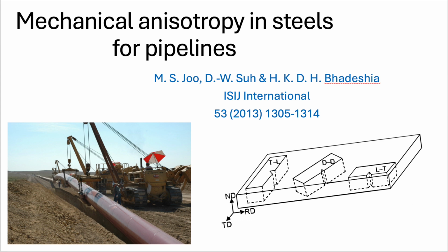It sounds completely backward, I know. Yeah. But it really highlights that the shape of the inclusions is the dominant factor, maybe even more than the total amount. So in the low sulfur steel, the few sulfides that were there got stretched out even more extremely during rolling? That seems to be the explanation. Yeah. They ended up with a higher aspect ratio, flatter, and longer, making them more effective weak planes. So the shape effect overwhelmed the benefit of having fewer of them overall.